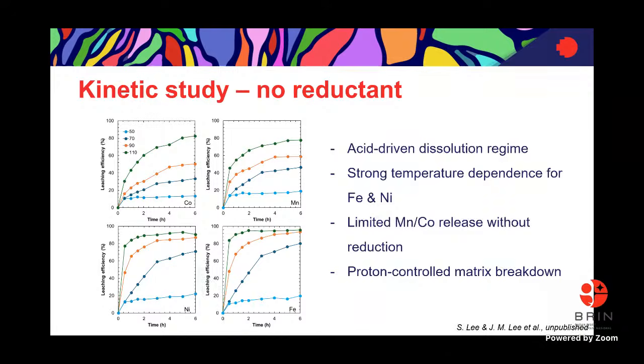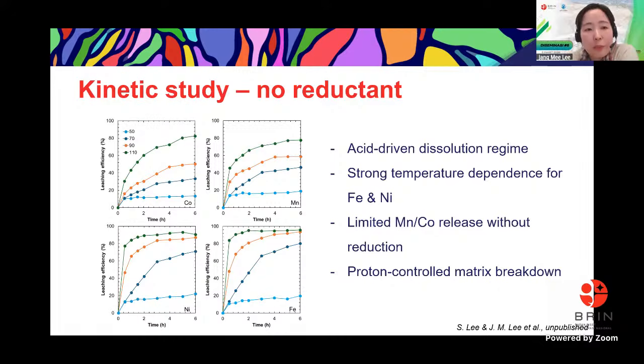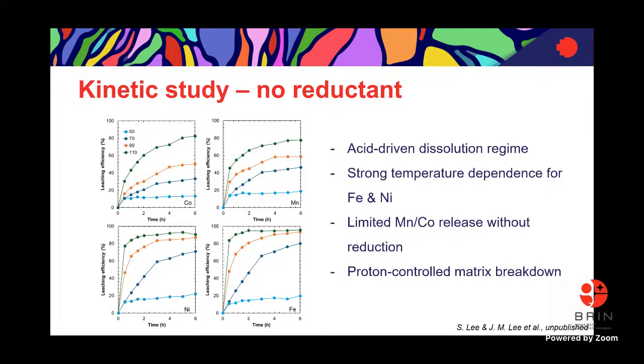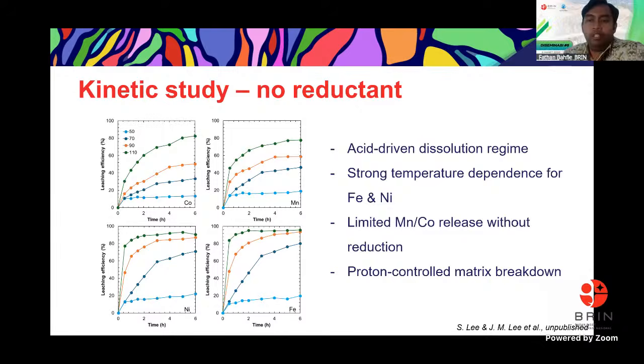I explained about the goethite firstly. Why? Because nickel associates in the goethite, majorly, right? And the goethite will be decomposed at 150 up to 300 degrees Celsius, according to our report on the mechanism of this process. It means we can easily get a nice reaction between acid and nickel oxide in that temperature range of 150 to 300 degrees Celsius. So in order to get a large amount of nickel recovery, but in your process just 110 degrees Celsius, maybe you can explain the process or the reaction mechanism, why at low temperature you can get so much nickel extraction.